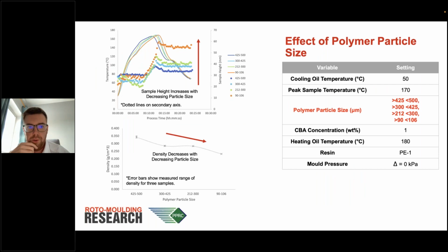Interestingly, it allows you to experiment with things that you wouldn't ordinarily be able to on an industrial scale without significant effort. So in this case, what I'm showing is the effect of polymer particle size on the foam height produced. And you can see that at 425 to 500 microns, you get a foam down here. But at 90 to 106, a much finer particle size, you get a sharp increase between the two in the foam height, and equally a reduction in the foam density that's produced. So that might suggest then that a finer particle size produces a more optimum foam, smaller bubbles, and more of them.